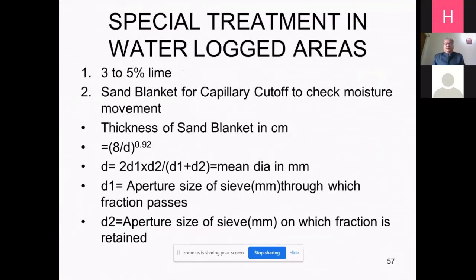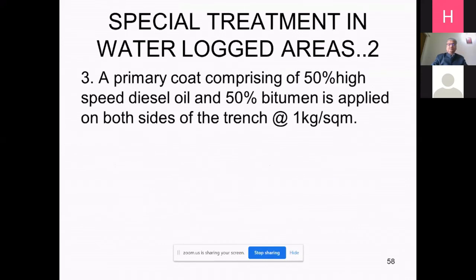Now some special treatment in waterlogged areas, you have to add 3 to 5% lime, and a sand blanket for capillary cutoff to check moisture movement. Then for that, the thickness of sand blanket in centimeter is given by 8 by d to the power 0.92, where d is 2d1d2 upon d1 plus d2. Basically, this is the harmonic mean of d1 and d2, and you can find it out. Or a third method may be a primary coat comprising of 50% high speed diesel oil and 50% bitumen applied on both sides of the trench.